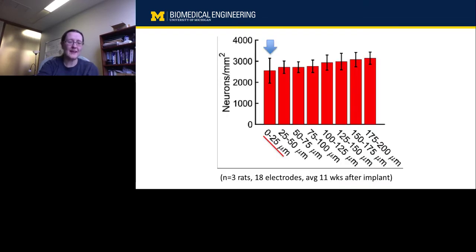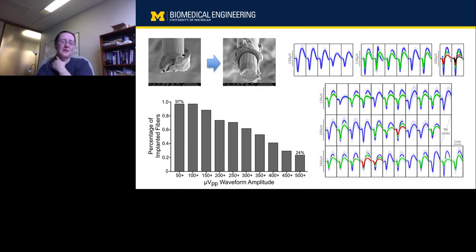I should also say that you'd expect the yield of the neurons to be very high if you're having these very high densities near the electrode tip. In some of our earlier histology work and some from other groups, there was very minimal damage to the neurons. And we saw this in the literature before we were able to slice the electrodes and visualize them. We saw that there was very little immune response. But we always had suspiciously low yield of neurons, even though we were having such a good immune response.